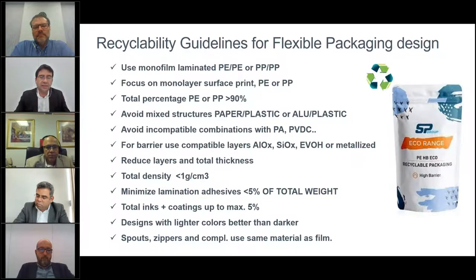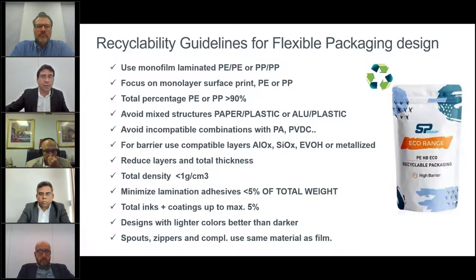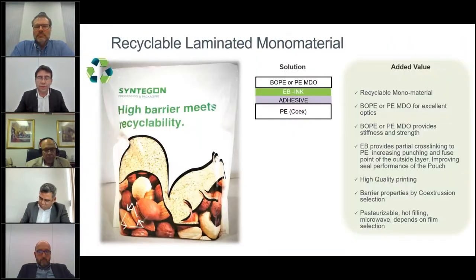To reduce the layers, the total thickness and the total density should be lower than 1 gram per cubic centimeter, and to minimize the lamination adhesives lower than 5%, as well as the total inks and coatings lower than 5%. For the designs, lighter colors are better, and the complementary spouts, zippers and others should be the same material as the film. With these recommendations, we did several